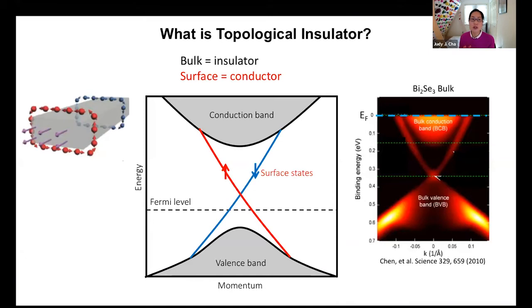For those of you in the audience who may not study topological materials, for material scientists and people who are interested in the properties, we can just consider this as a regular bulk material, but with special surface properties. A topological insulator is a bulk insulator or bulk semiconductor, as denoted by the shaded areas in the band structures, but with topologically protected surface states, which are denoted by these two lines. The special thing about these two surface states is that the spin of the electrons is locked to the direction of the electron motion. We know this is true from a lot of ARPES measurements, angle-resolved photoelectron spectroscopy, which directly image the band structures and prove the existence of these surface states. Pictorially, you can imagine electrons living on the surface that transport.